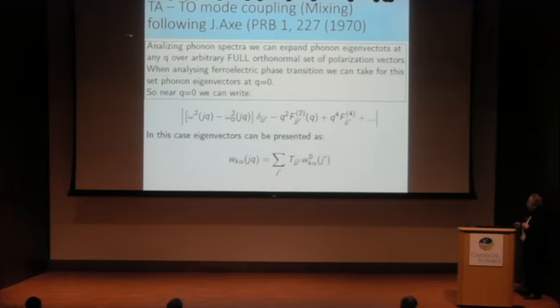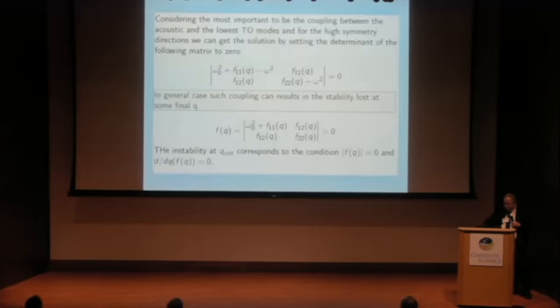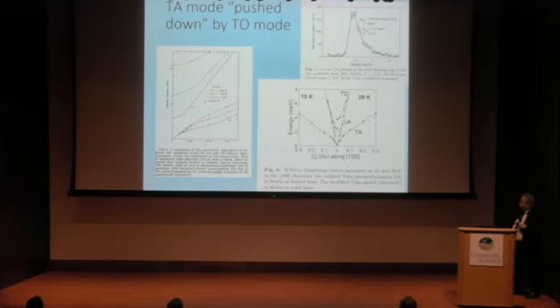So, let's say that analyzing phonon spectra, we can expand phonon eigenvectors at any Q on an arbitrary full orthonormal set. And in this case, first we will start to do it at Q equals 0. I'll go through the calculation. So what we can get if we expand it. In reality, that's what we observed in pure potassium tantalate. You see there is a soft mode, but we do have a strong change of the transverse acoustic.